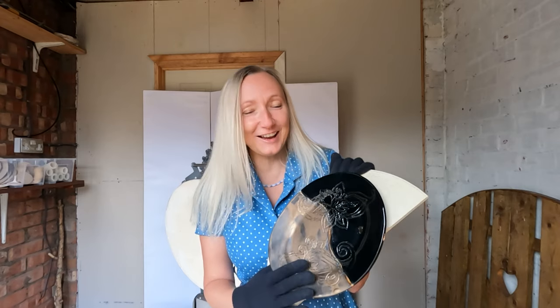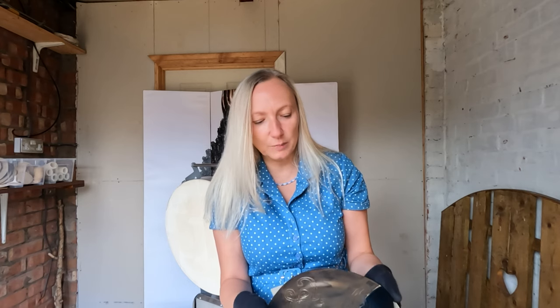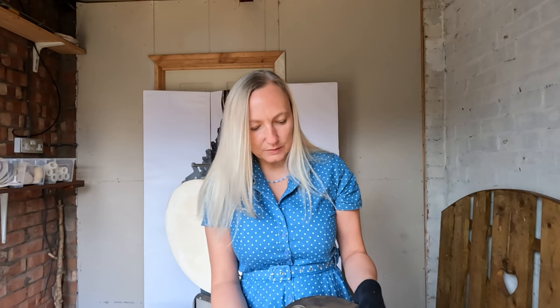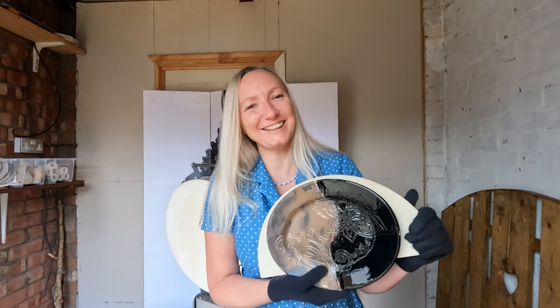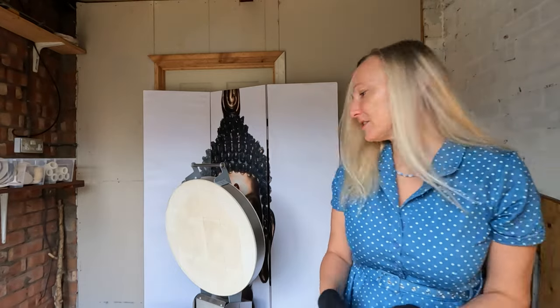As I've tried to get it off it's cracked, which is a shame because this is actually the middle piece of a set of three. I'll have to redo it, but I'll have to put firmer feet on — that's something to note. I only put tiny feet on it, so they obviously weren't big enough to support the weight. That is really something to note for myself. So my first shelf lost at kiln opening nine — that's a shame, but it is a learning curve.